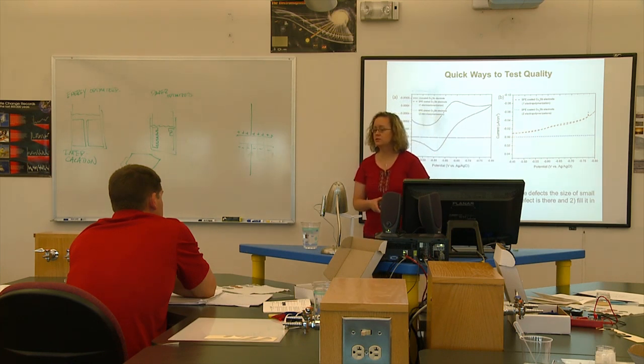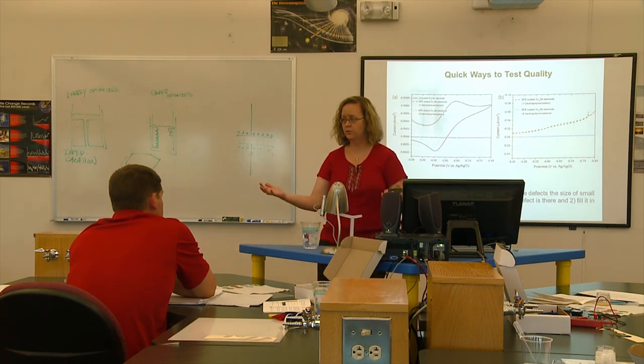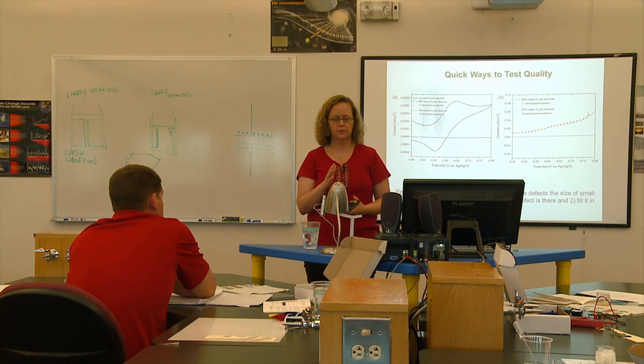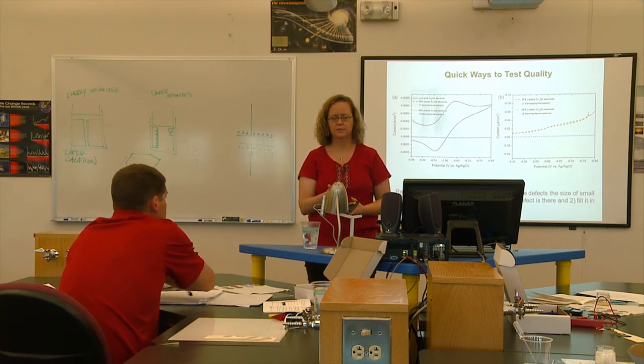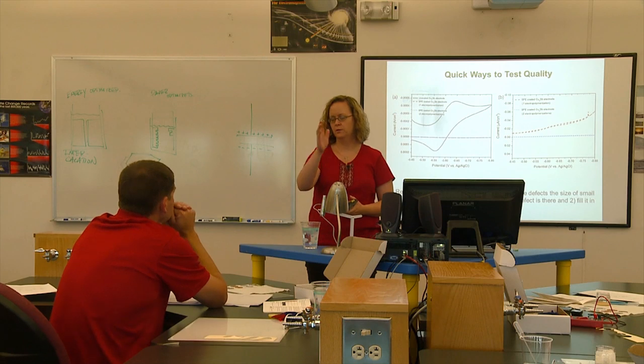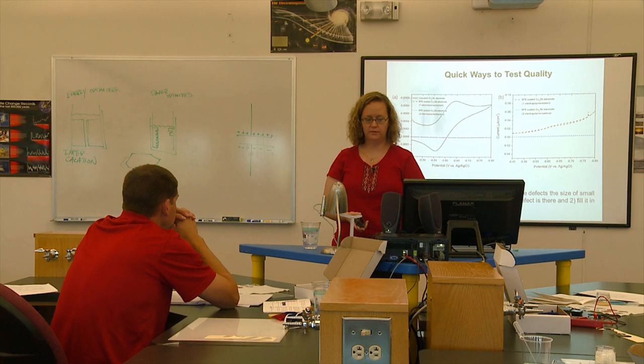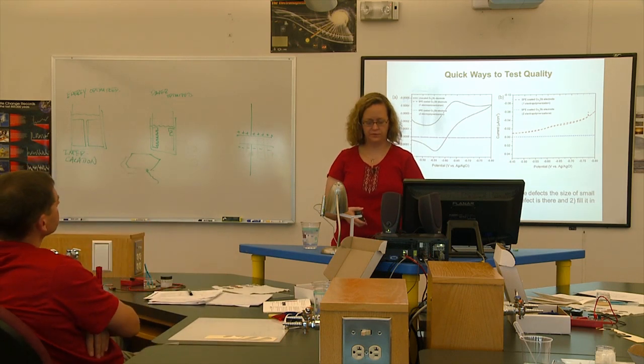So this is all done in water. It's all done open in air, and it takes about 30 seconds for the test, and then if you see a mistake, you have to rinse, that's a minute. You put it back in the polymer solution, and then the next pulse is about a 4 minute pulse, and then you just check it again. So this is how we know if a defect is there or not, and then also how we fix it.